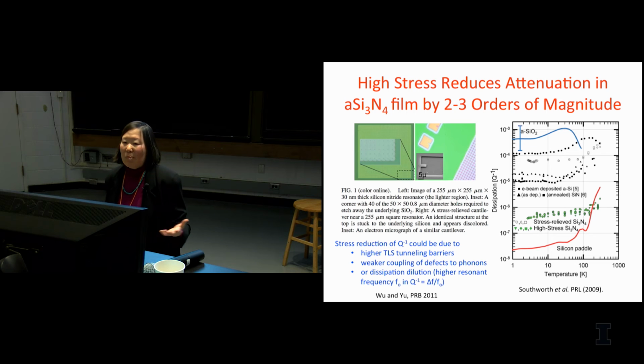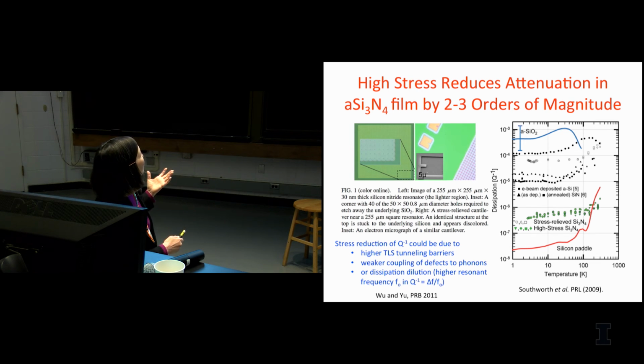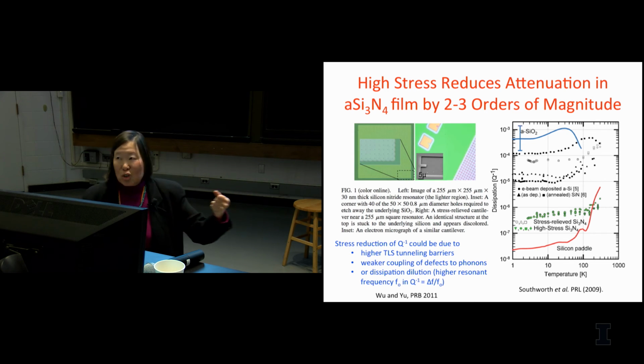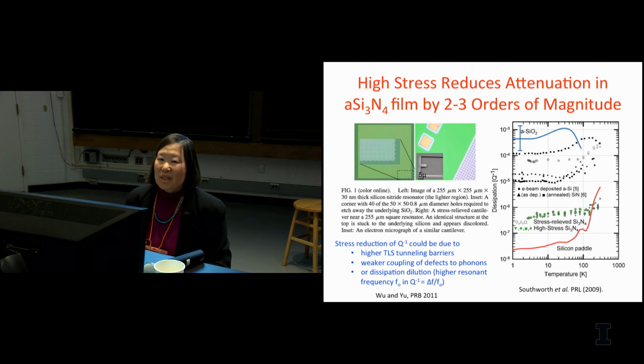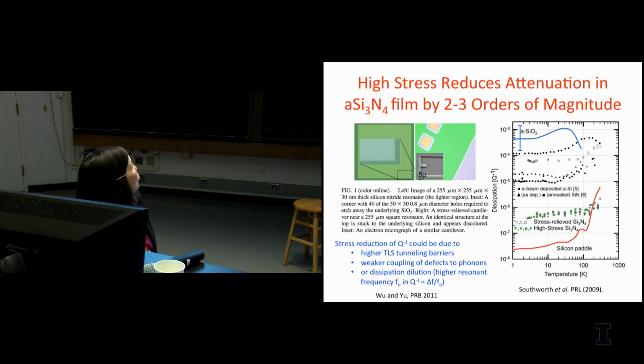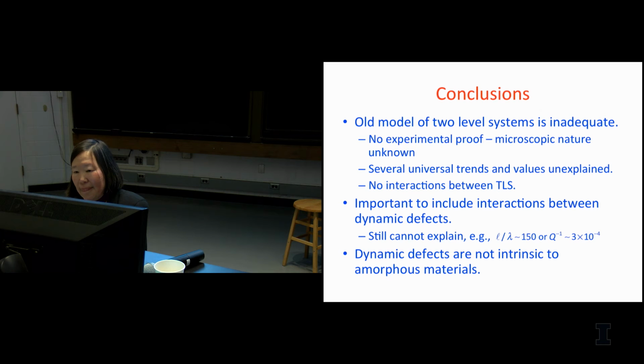Why does this come about? If you believe in tunneling, maybe there are higher tunneling barriers or weaker coupling of the defects to phonons. Or Peter Saulson suggested dissipation dilution. Basically, Q inverse is the ratio of delta f over f naught, the resonant frequency. If you have high stress, maybe you increase the resonant frequency and therefore drop Q inverse.